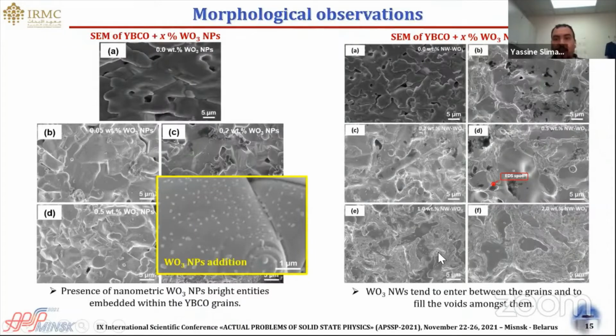In the case of nanowire-added samples, we found that tungsten oxide nanowires tend to enter between the grains and fill the voids between them, providing metal bridges network among superconducting grains. Consequently, the connectivity between the grains will be enhanced and the porosity will be reduced.